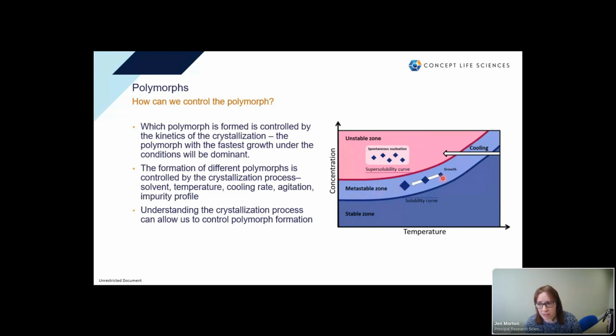In the middle, we've got the metastable zone. And this is the zone where typically we would try and seed the solution. So the solution can persist in the metastable zone, but you can trigger it to start precipitating. So this is where we would like to seed, and the conditions here are perfect for crystal growth. So for good control of a polymorph, we want to see more crystal growth than nucleation. And the polymorph that can grow the fastest under those conditions in the metastable zone is the one that will dominate. And I think that Carmen will come back to this diagram later on and start to explain how we can find out where these solubility curves lie for a given solution.